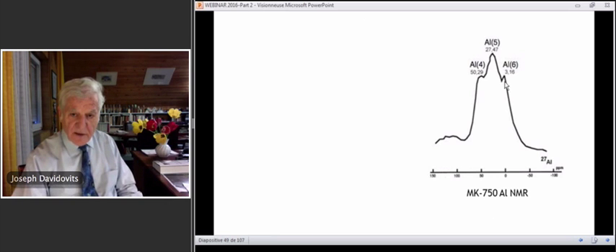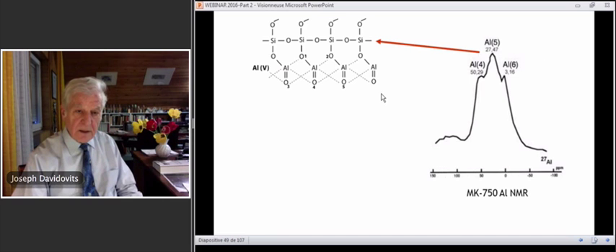And if we look at what we have under nuclear magnetic resonance spectroscopy of this metakaolin, we have 3 resonances. One that is the most important, this is Al5. This is the one that reacts. And this is what we must write in terms of chemical structure. We have SiO, then OAl double bond O. The aluminum is trivalent, one bond to oxygen and double bond, that is 3, but it is surrounded by 1, 2, 3, 4, 5 oxygen. Geometrically, it is penta-coordinated.